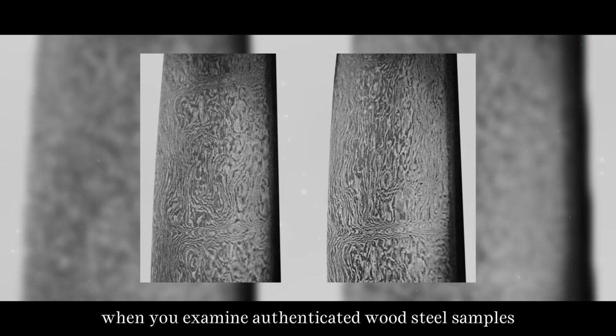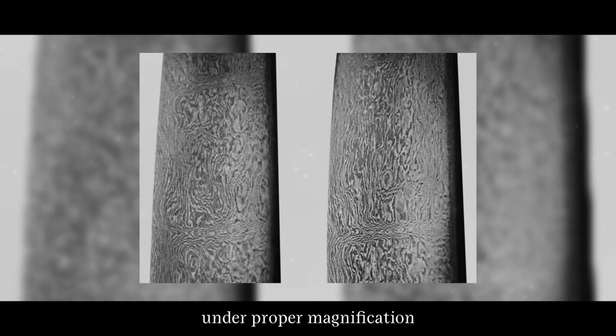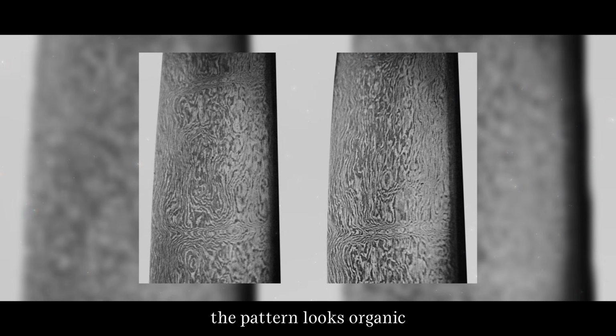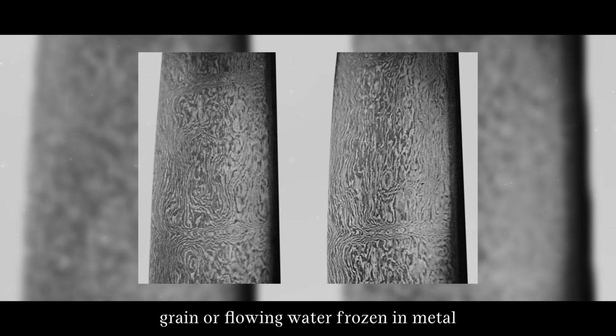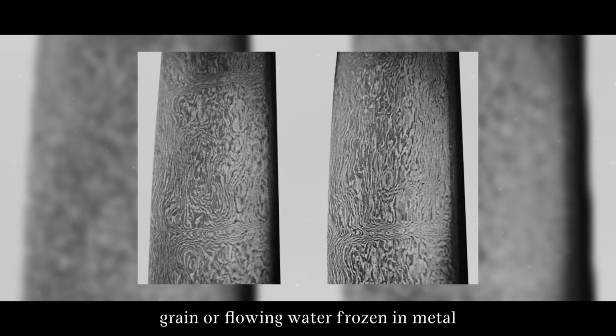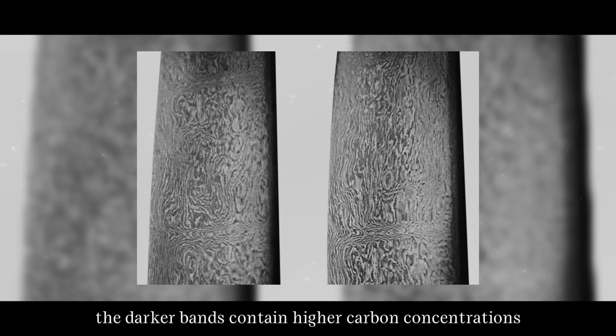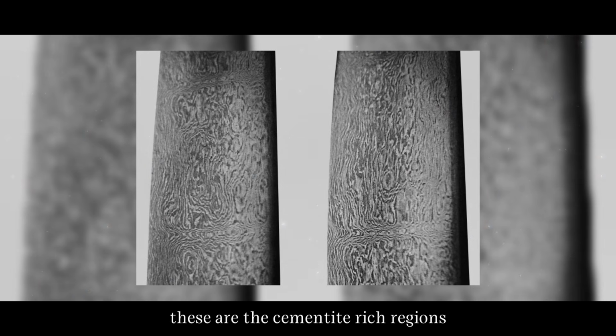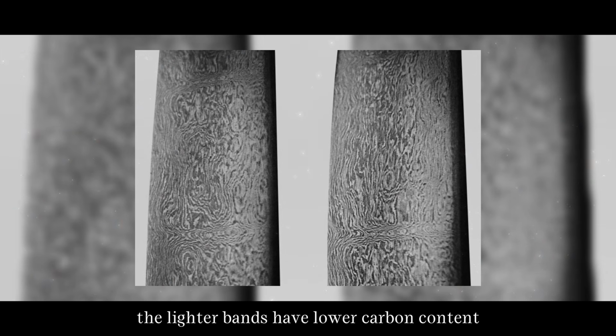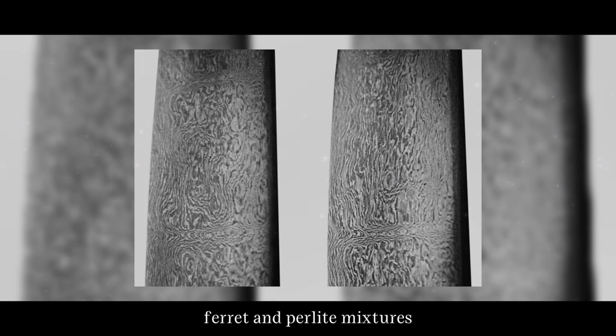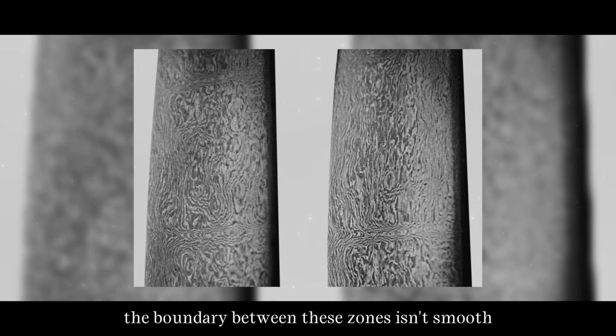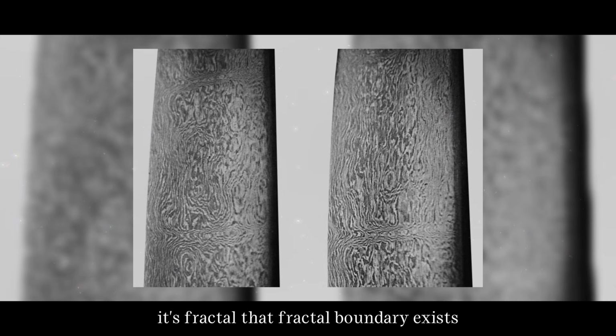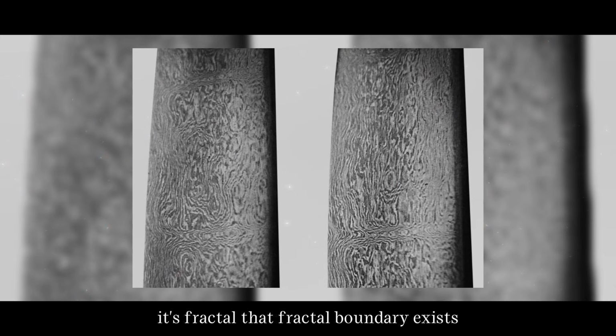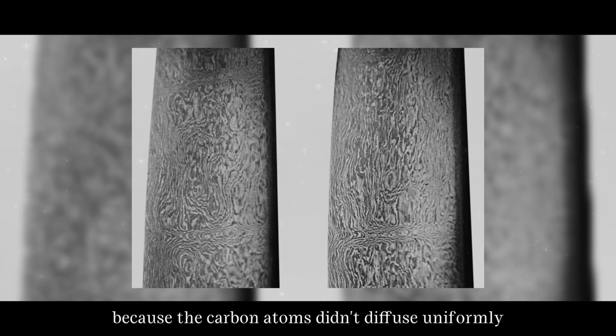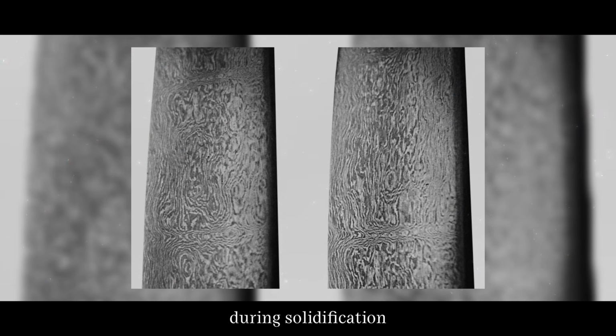When you examine authenticated wootz steel samples under proper magnification, the pattern looks organic. It resembles wood grain or flowing water frozen in metal. The darker bands contain higher carbon concentrations. These are the cementite-rich regions. The lighter bands have lower carbon content, ferrite and pearlite mixtures. The boundary between these zones isn't smooth. It's fractal.